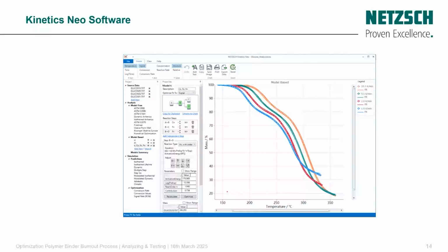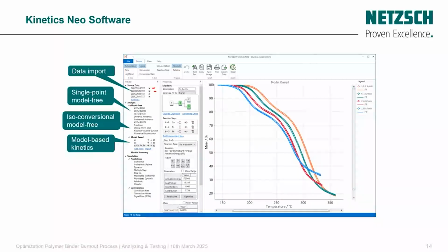And here we have a screenshot from the software that is showing us the different parts of it. So we have the data import or the source data. Here we have 4 files, as you can see, which means that we have different heating rates: heating rate 1, 2, 5, and 10. Then we can go to the second step, which is the kinetics analysis, and it's divided into 2 parts, the model-free and the model-based. And then we have the model design, which gives us the possibility to describe our model by competing, consecutive, or independent steps.